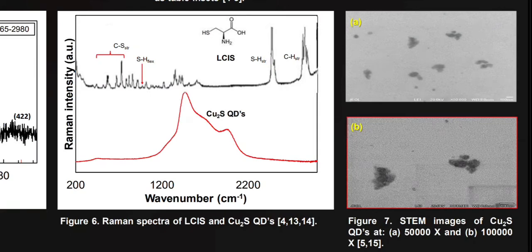From STEM images, it can be seen that quantum dots have dispersed diameters that comprise values from 9 nanometers to 52 nanometers with a spherical shape tendency. Some agglomerations can be seen. Nevertheless, the suspension stays stable without visible precipitates. These observations are opposed to the previous ones.